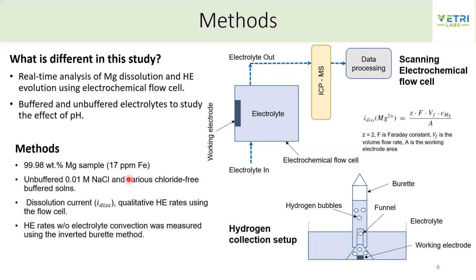The methods used for this study were they chose magnesium which had about 17 ppm of iron, and they used unbuffered 0.01 molar NaCl and some buffered solutions. Their idea was to see dissolution current, and then they also wanted to see a semi-quantitative kind of hydrogen evolution rates.